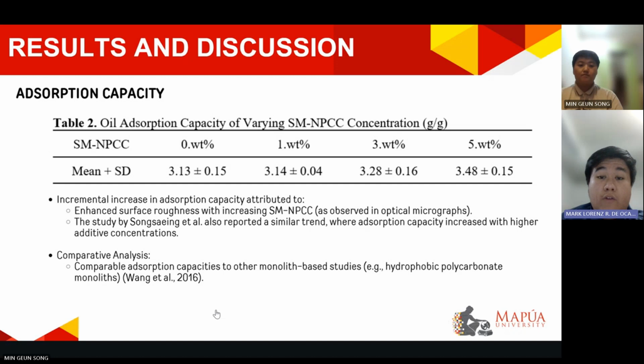This observation is consistent with the findings of, again, Songsang et al., who reported a similar trend in their study. They found that adsorption capacity increases with higher additive concentrations, which, again, aligns with the morphological changes and pore size increase seen in this work. Comparatively, the adsorption capacity of the PLA-SM-NPCC composites is comparable to other monolith-based studies, such as hydrophobic polycarbonate monoliths studied by Wang et al. in 2016. Overall, the results demonstrate that the PLA-SM-NPCC composites are effective in adsorption of these materials. Next.